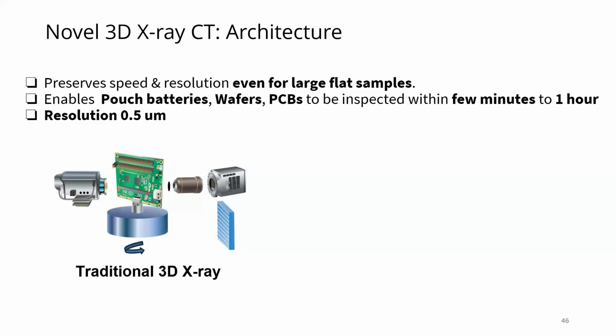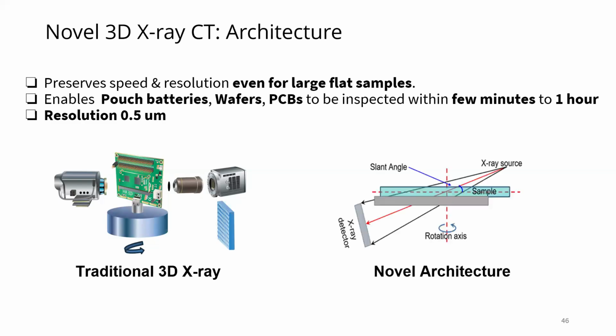This is a schematic of a traditional 3D X-ray microscope. So if you have a flat object, obviously you find that you have to space the source from the detector quite far away during the rotation. And what if this material is right in alignment with the source and the detector? The X-rays have to go all the way through a lot of materials, and that gives rise to a huge amount of artifacts called beam hardening artifacts. Now, it is also very slow using this type of traditional approach where the sample is rotated this way. So what we have done is we have a patented architecture which allows us to spin the samples and the X-rays come in at an angle.